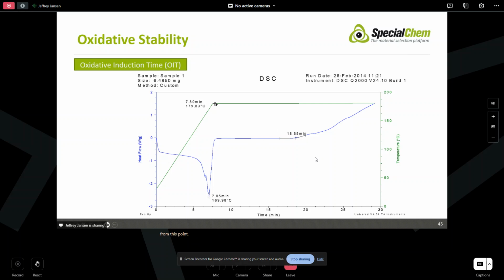Now, we would know that this is a little over 8 minutes. So we basically got 11 minutes between when we turn the oxygen on and when we start to see this exothermic shift. This represents oxidation of the polymer, the polymer undergoing a chemical reaction with oxygen, which means that our antioxidants have been consumed. This is the induction time. This is the time that exposure to oxygen at elevated temperature has consumed all of our antioxidants.